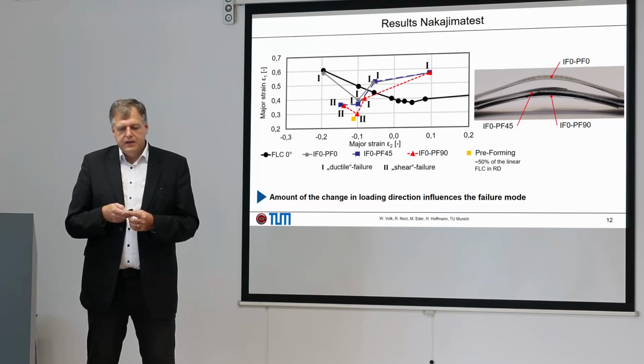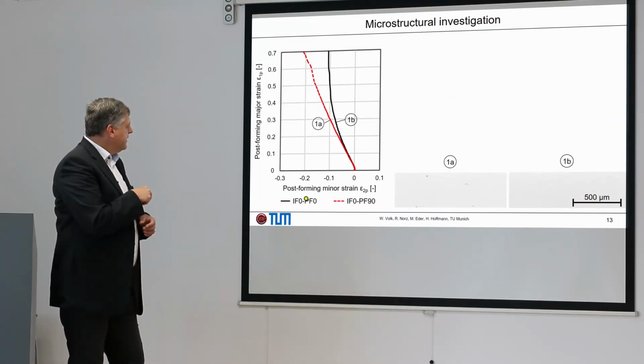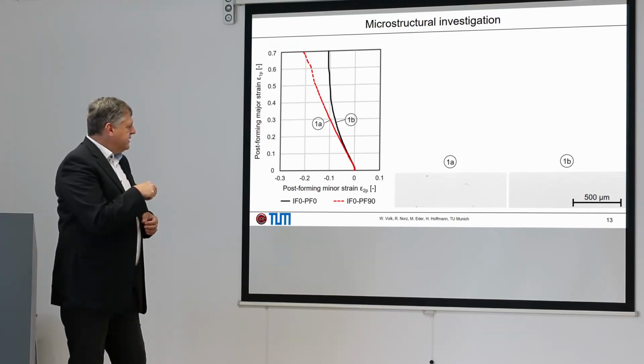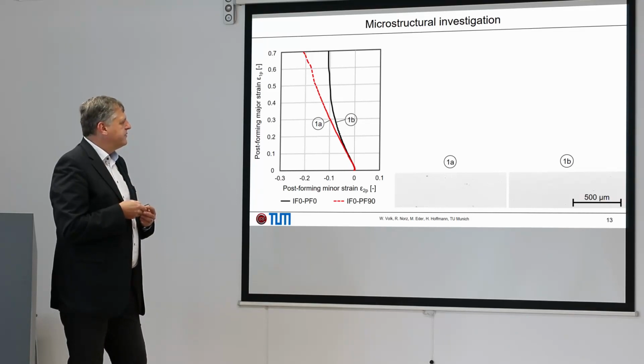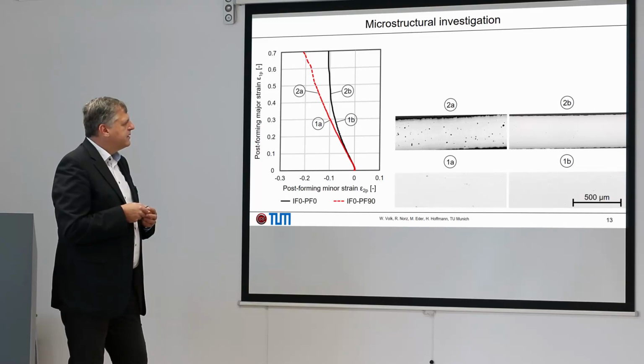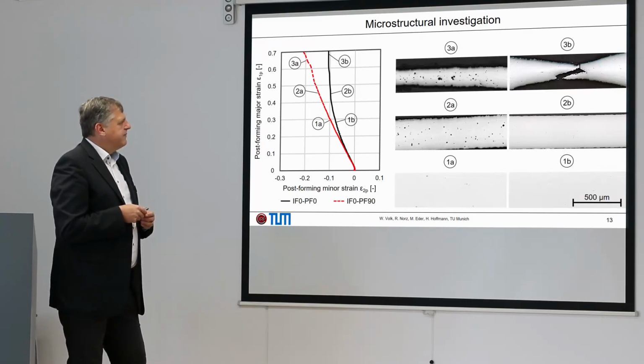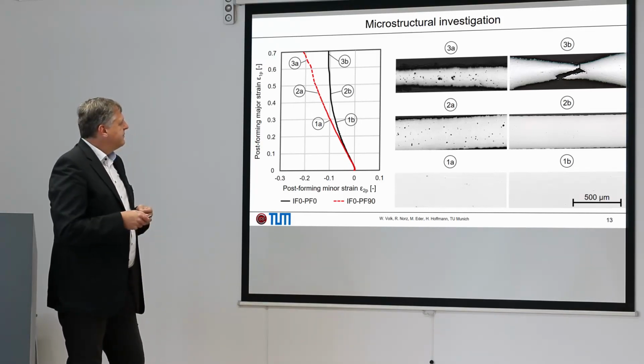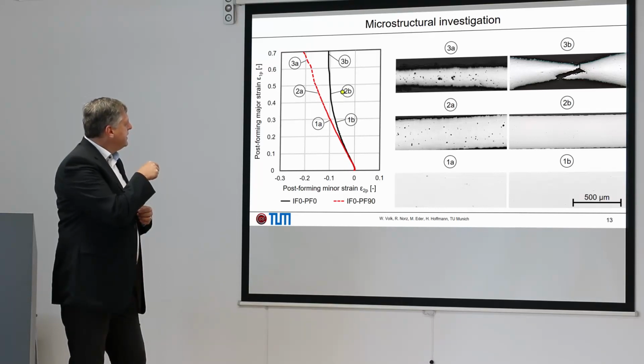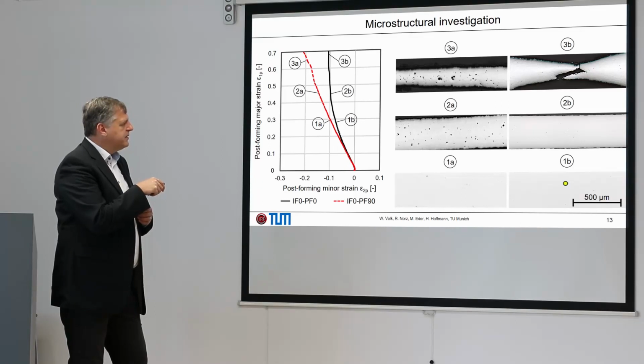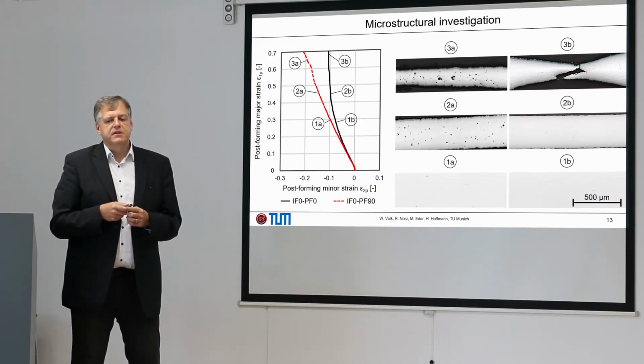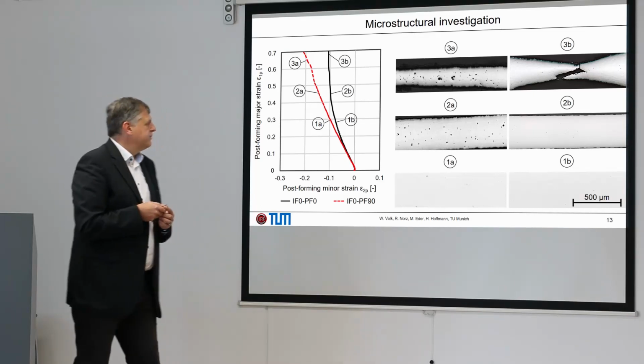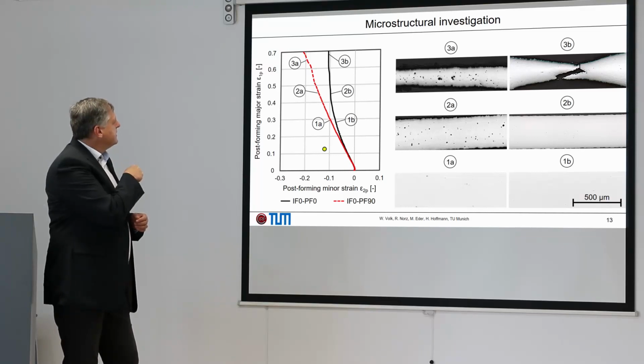And what is done now? Here we see for this 0,0 and the 90 combination, the strain path after the preforming step. So this is a moderate first start of strain. Then we have an ongoing intermediate step, and then finally where we have the failure of the specimen. Here on the right-hand side, conventional view 1B, 2B, 3B, we see nearly the homogeneous specimen. Then after start of diffuse necking, some small voids which can occur, and finally the crack starting out of the middle of the specimen in the well-known representation.